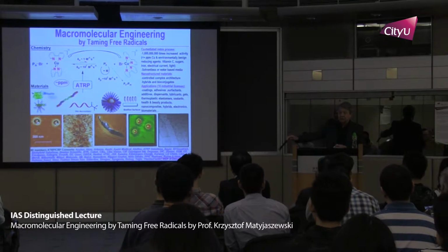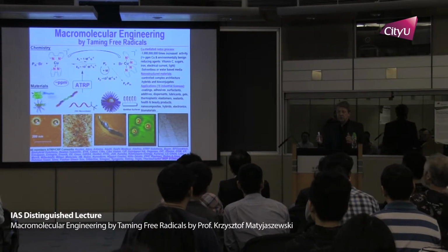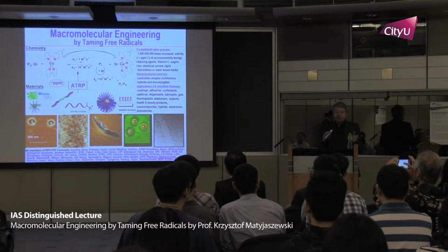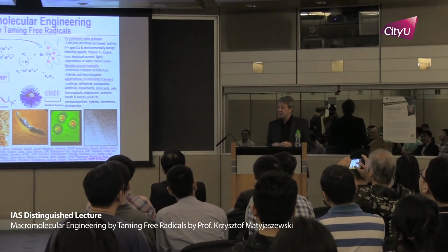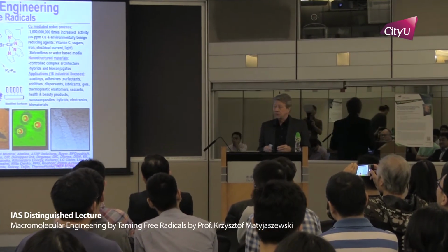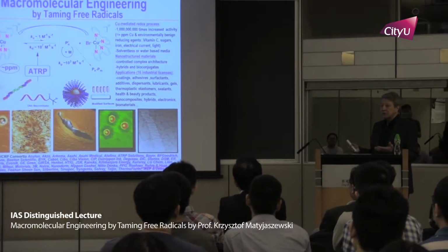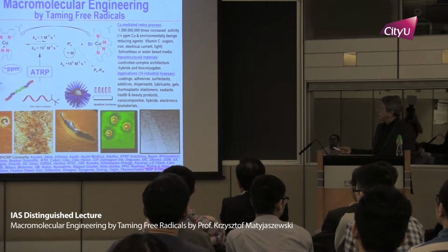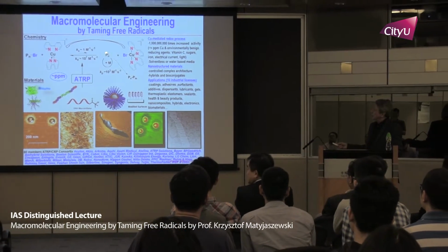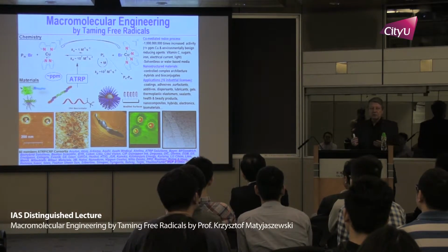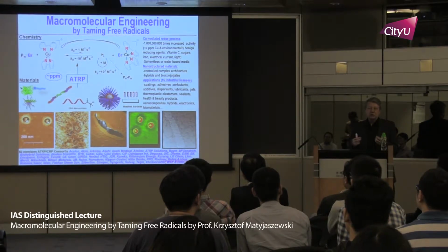Free radicals are generally very reactive species, very difficult to control. Whether in politics, they kill one another, they never listen to what you want them to listen to, and in chemistry it's the same. Radicals terminate very fast, in fact as fast as they meet, with diffusion-controlled rates. Typically in a radical polymerization, the lifetime of a radical is roughly 1 second. During 1 second, you cannot do much chemistry, because it is too short a time to add a second monomer or some other reagents.